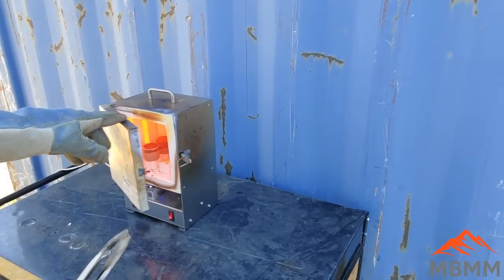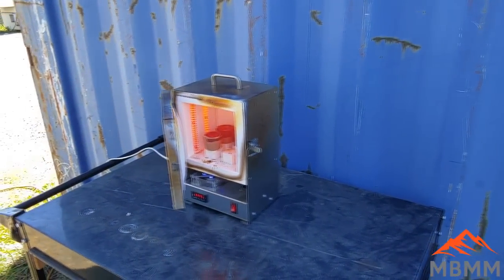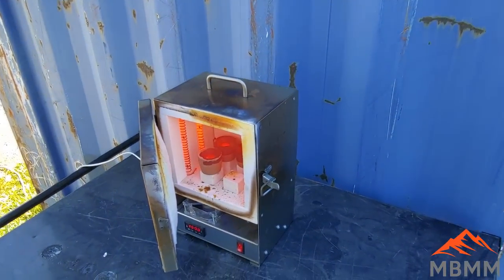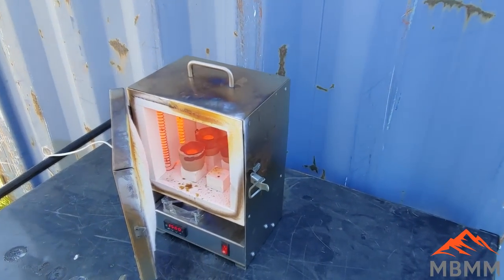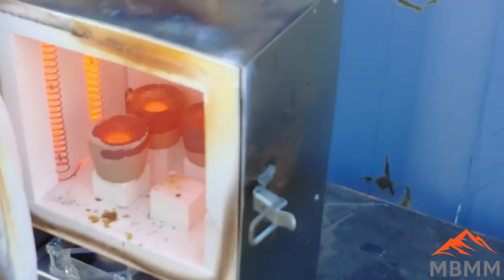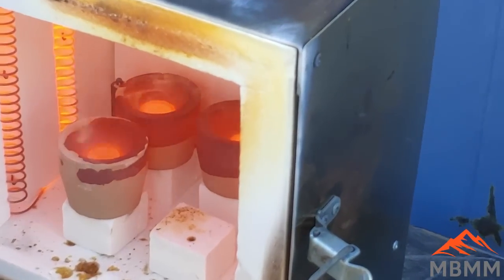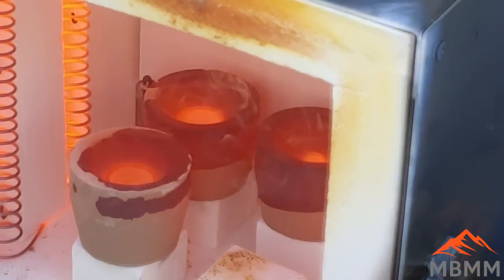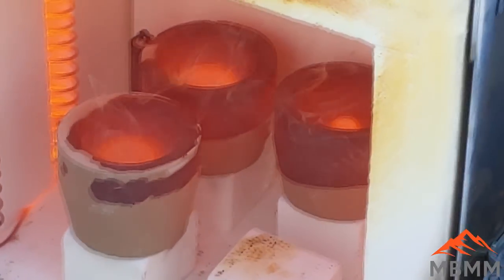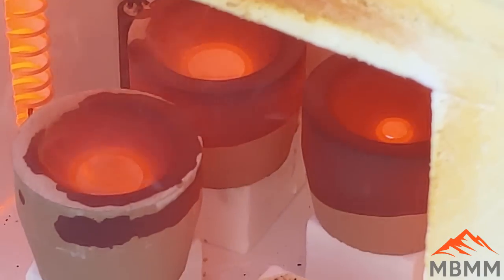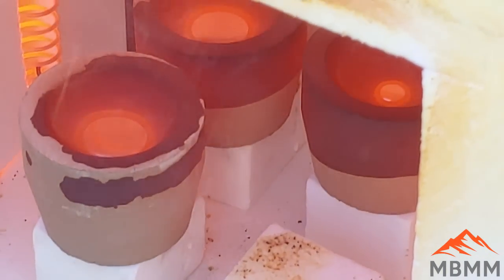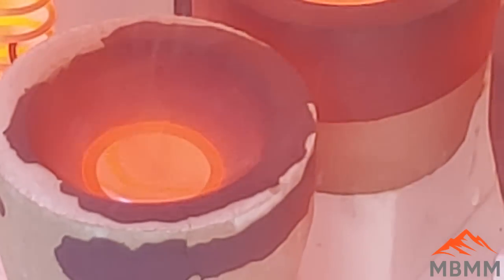So it turns liquid, and it forms a layer of lead oxide on top. It looks scummy black. Then as you raise the temperature more, the lead oxide becomes liquid. It actually melts at 1640 degrees Fahrenheit. Once it melts, it looks like little raindrops on top of the lead metal. Once it becomes molten, it rolls off the lead bead, and when it touches the cupel, it sucks into the cupel like a sponge.